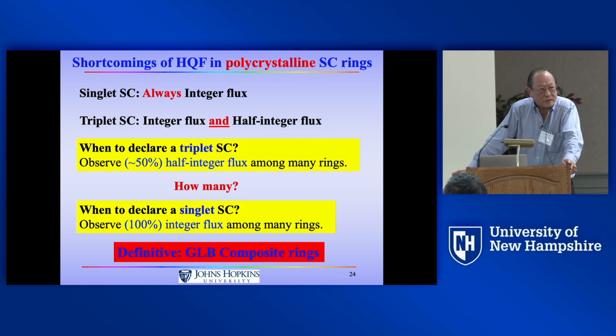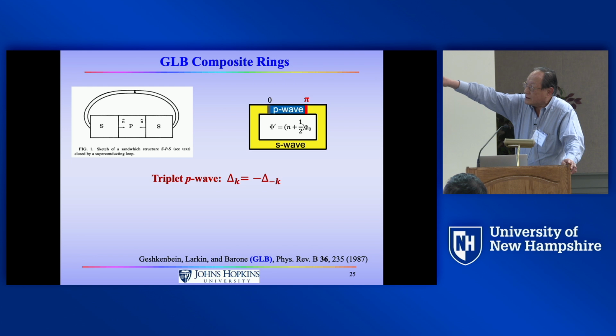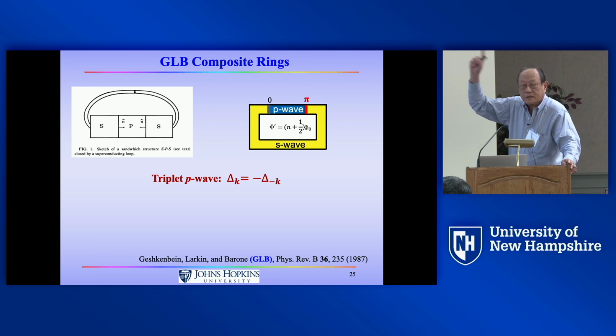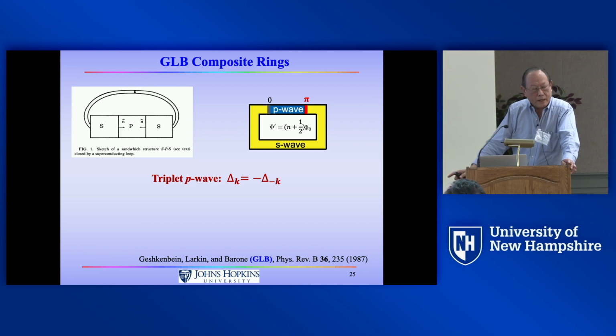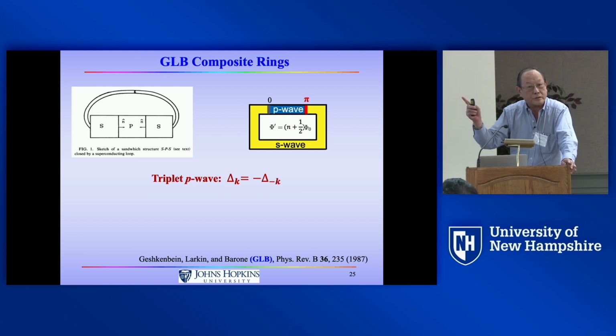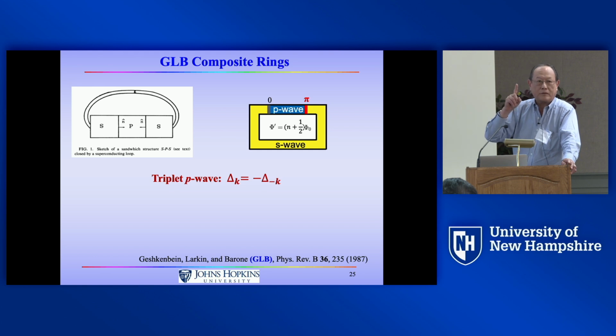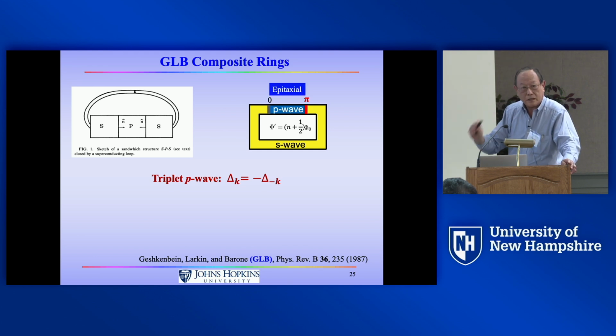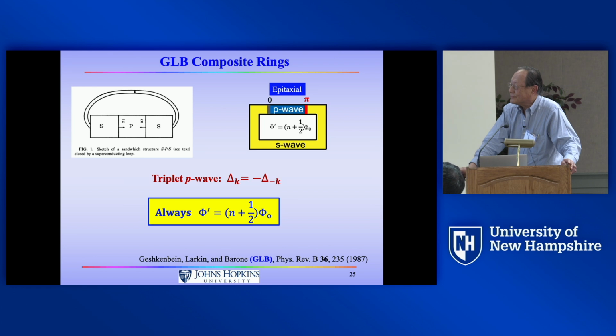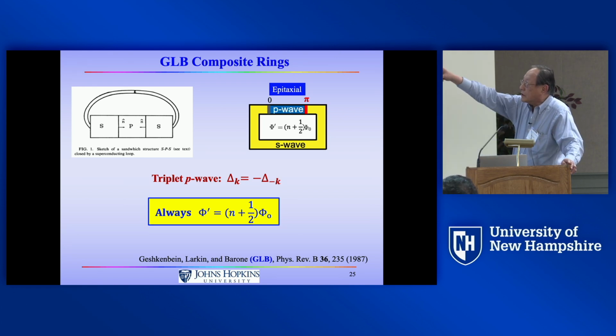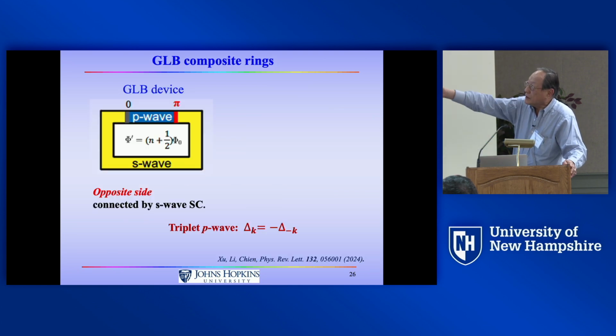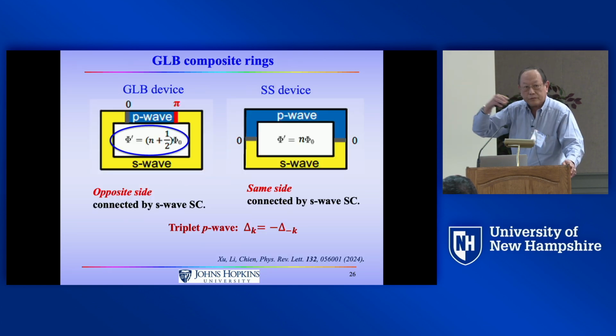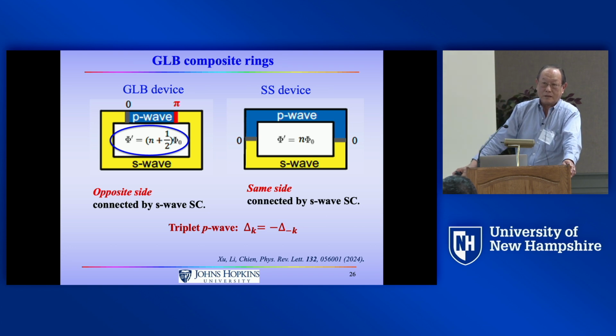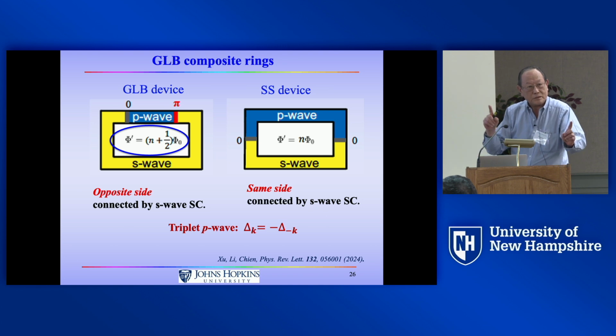Is there any way? Yes. You can follow what the theorist said. The left is the theorist. The right is the experimentalist. You make a triplet superconductor connected with a singlet. The 2 opposite ends of the triplet must change sign. I don't care which side changes sign, it changes sign. Therefore, this ring will have half flux. No other choice. Of course, this superconductor has to be a single crystal or an epitaxial film. So you will do 1 measurement. Always half flux, because the S wave is connected to the opposite end. If you change to a different structure on the right, the S wave connects to the same side, you'll never get half flux. You always get integer. So these 2 experiments, you only do once.